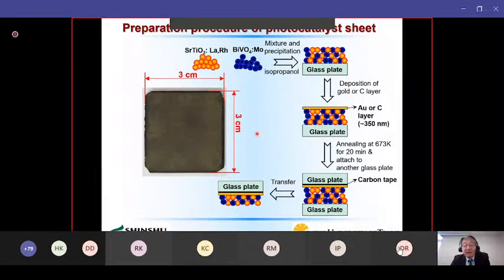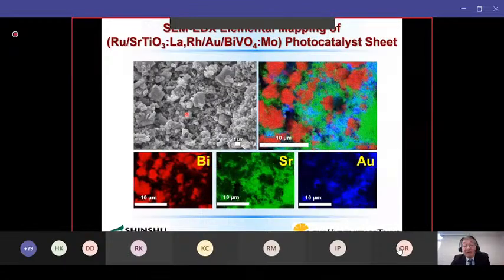So after ultrasonication to remove such physically adsorbed particles, we can get this kind of photocatalyst sheet prepared on a glass plate. And if we look at this surface by SEM, as you see here, the structure is not really so sophisticated. The red dot indicates the oxygen evolution photocatalyst. The green dot indicates the hydrogen evolution photocatalyst. And the blue dot indicates a contact layer, in this case gold. This is the total feature of this photocatalyst sheet.